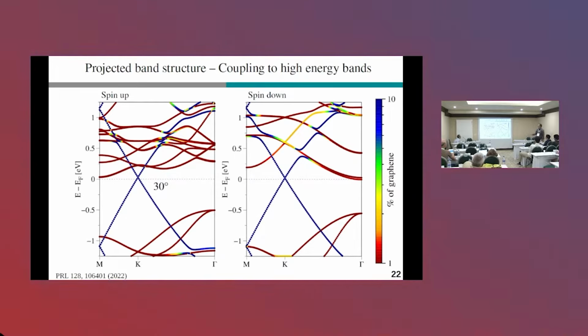And in fact, for the spin up case, you will find no coupling to these low energy substrate bands, while there is quite a weak coupling to these high energy levels. In contrast, in the spin down manifold, you find quite a strong coupling of the Dirac states to these high energy levels. And this is what pushes the spin down Dirac state to lower energies for this case.